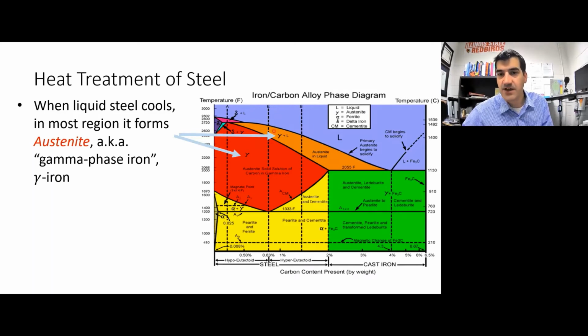All right, so when you first start cooling it down, you get a combination, like a slushy, of gamma, austenite, and liquid molten metal. As you continue to cool it down, you get fully solid material. This is all austenite in this region right here. I know you can't see my pointer real well because my pointer is red, but this is austenite right here. And then like before, here is our upper critical temperature, which varies depending on the carbon content. And here is our lower critical temperature, which is horizontal and a consistent 1333 degrees Fahrenheit. Below that, depending on how much carbon you have, you'll either get all ferrite and perlite grains, or if you have more than about 0.8% carbon, you're going to get all perlite and cementite grains over here.